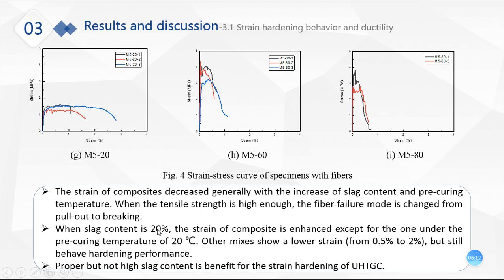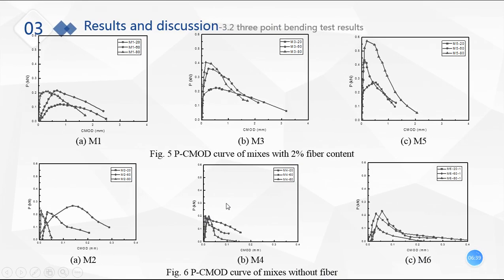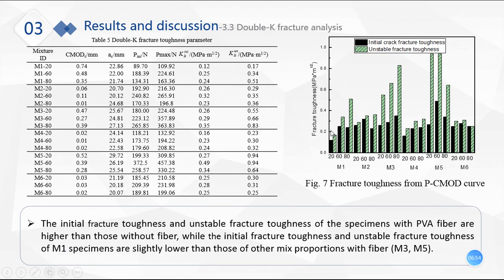When slag content is 20%, the strain of composite is enhanced except for the one under the pre-curing temperature of 20 centigrade. Other mixes show a low strain but still behave with hardening performance. Proper but not high slag content is beneficial for the strain hardening of the specimens. Let's look at the relation curves of load and crack mouth opening displacement with and without fibers.